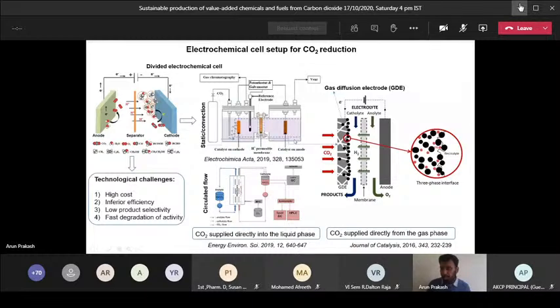I told you it is a big challenge. How can you control your selectivity? So far I introduced what a CO2 system is and several things I have discussed. But next we move on to the selectivity. You are using an aqueous electrolyte, you have protons, so the protons will adsorb. The hydrogen binding strength is very important. If hydrogen or proton gets strongly adsorbed, then it will be reduced back to hydrogen. So the hydrogen evolution will dominate your CO2 reduction. Strong proton binding leads to high hydrogen evolution reaction activity, so low selectivity for CO2 reduction.